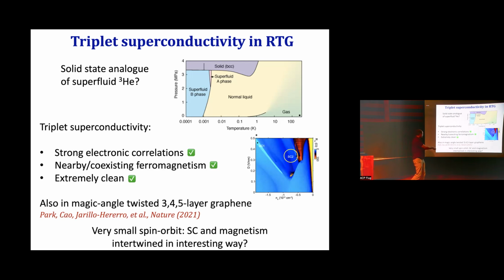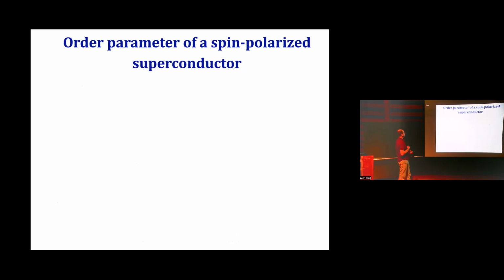In addition to that, graphene is a very light element, which means that it has very, very weak spin-orbit coupling. The spin is almost independent of the orbital degree of freedom, which means that in this superconductor, as was mentioned before, we have a new degree of freedom, which is the direction of polarization of the spin of the Cooper pair. The question is, how does that intertwine with the superconducting degree of freedom in an interesting way? Okay, and I'll just flash an argument.